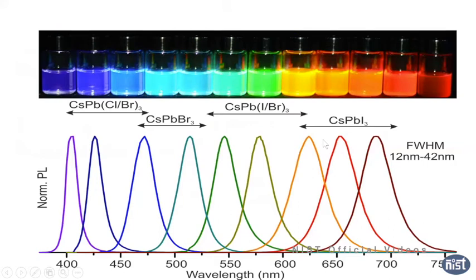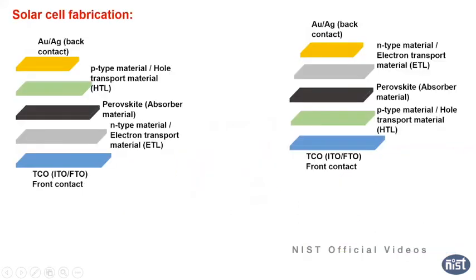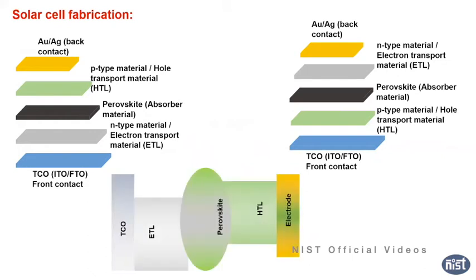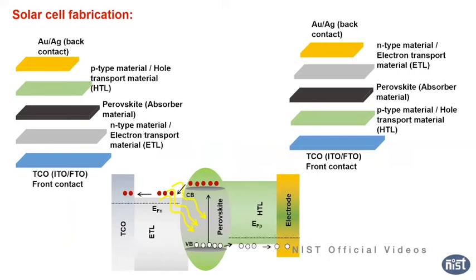It's again perovskite quantum dots, and we have started working on solar cells with perovskite quantum dots. We use the perovskite absorber material in between the common layers like the N-type material, P-type material, and hole transport layer. Generally for the N-type material we use titanium oxide and other things, but we use the perovskite quantum dots to see how the solar cell works. So this is basically how the solar cell works, with the transparent conducting oxide and a gold electrode. You shine light on the perovskite, the exciton is generated, the electron goes to the transparent conducting oxide side, the hole goes the other way, and so you have a circuit.